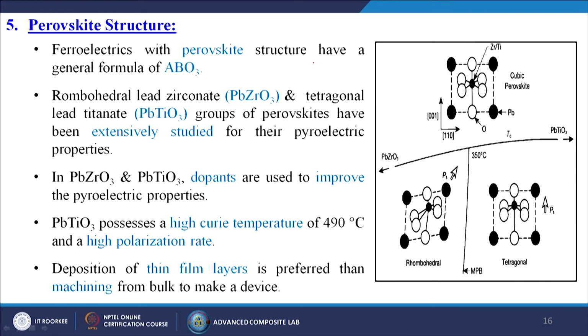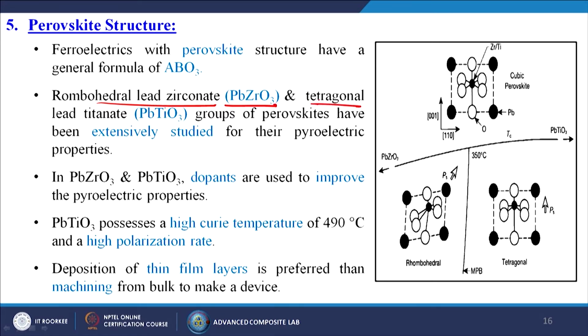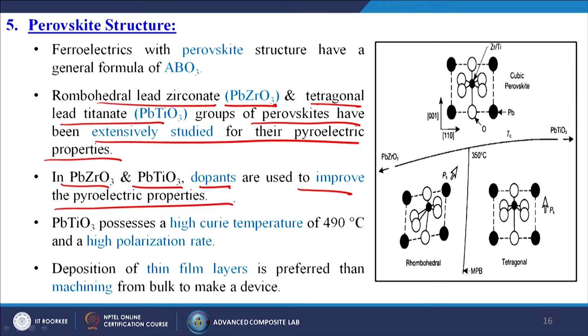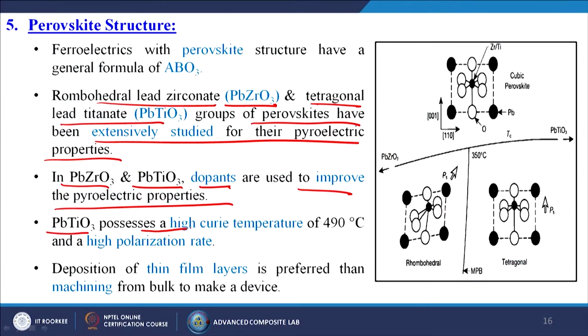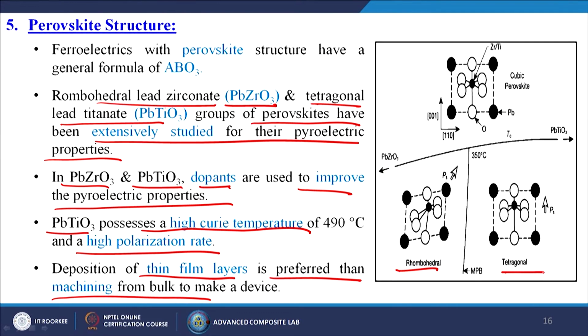Next is the perovskite structure. Ferroelectrics with perovskite structure have a general formula, basically ABO3. In this particular case, rhombohedral lead zirconate PbZrO3 and tetragonal lead titanate PbTiO3 groups of perovskite have been extensively studied for their pyroelectric properties. In PbZrO3 and PbTiO3, dopants are used to improve the pyroelectric properties. That means we are introducing certain third party materials inside the system to increase the efficiency. PbTiO3 possesses a high Curie temperature of 490 degrees centigrade and a high polarization rate. Deposition of thin film layers is preferred over machining from bulk to make a device. So, basically perovskite materials also have different crystal structures like rhombohedral and tetragonal. Based on the material configurations and the dopants, we can change the crystal structure of the perovskite materials so that it can give you the maximum efficiency.